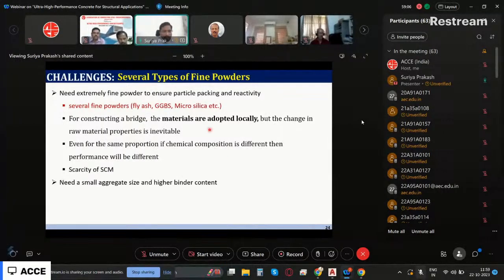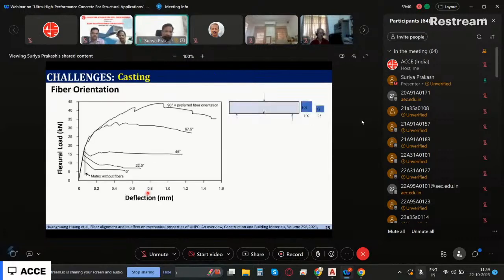Now, how long we are going to use this thermal power plant and get fly ash from there is not known, because now people are developing alternate power sources also. But currently thermal power plant is still a major power generation source, but how long that will continue, we don't know. So scarcity of SCM is also one of the things. And we need to have a very small aggregate size and higher binder content. And so because of that, cost will go up. And the moment you reduce your aggregate size and the quantity, creep and shrinkage issues also will become higher. So these are all some of the challenges.